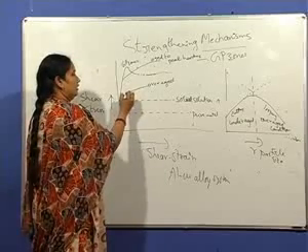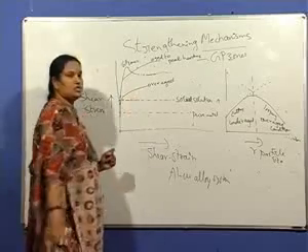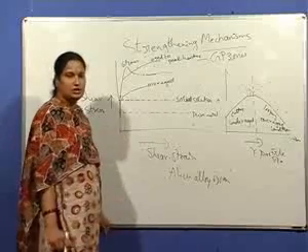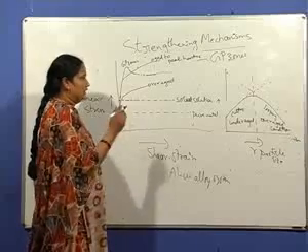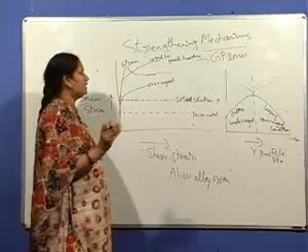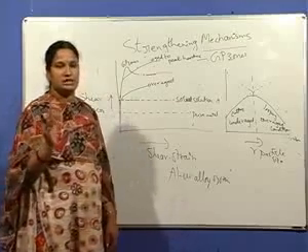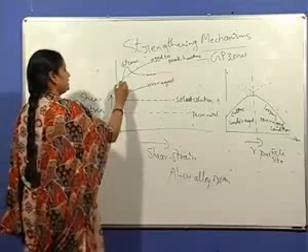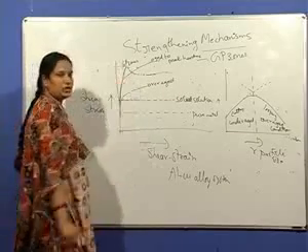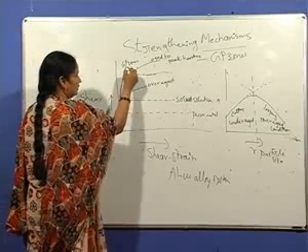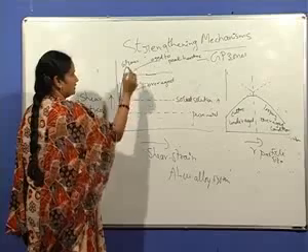But the rate of strain hardening is low, that is, the slope of the curve is low for solid solution. Then once aging starts, the initial transition phases formed are GP1 and GP2 zones. So the yield stress increases significantly, and a slight yield drop occurs.